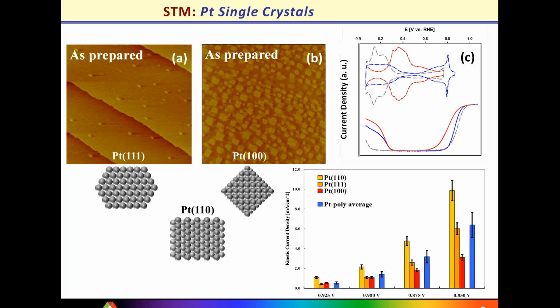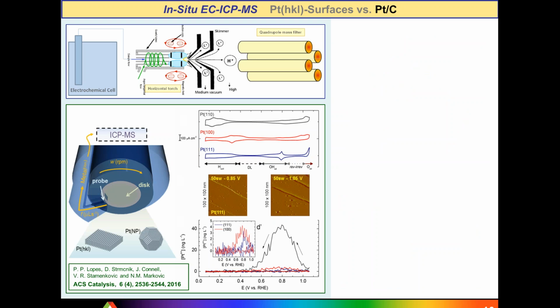So the most active surface is 110 and the least active surface is 100 in case of non-absorbing electrolytes such as perchloric acid. Situation is quite different in strongly absorbing electrolytes, and so this is a slide which reflects activity, and what is going on with stability is something which was just recently revealed from our group again.